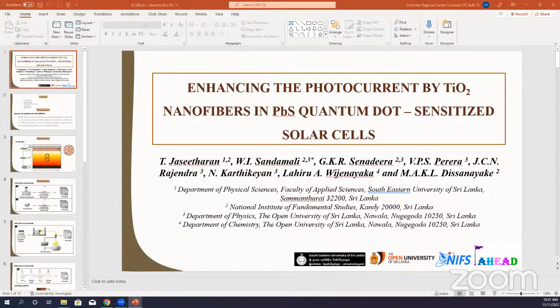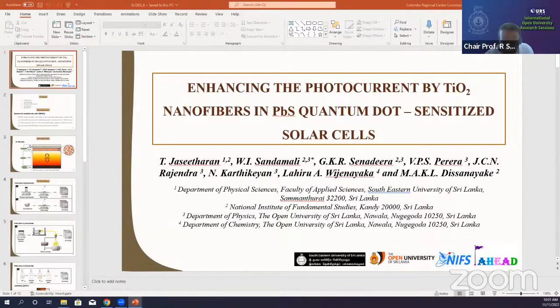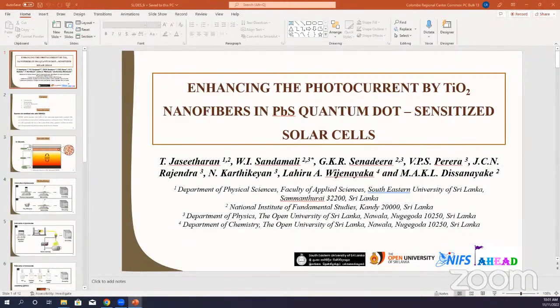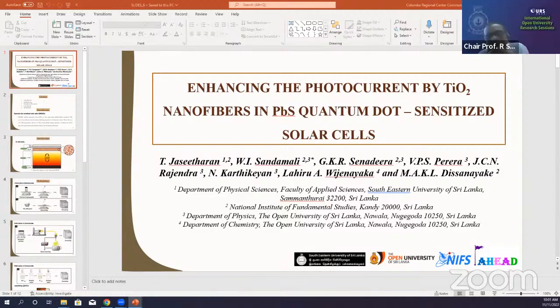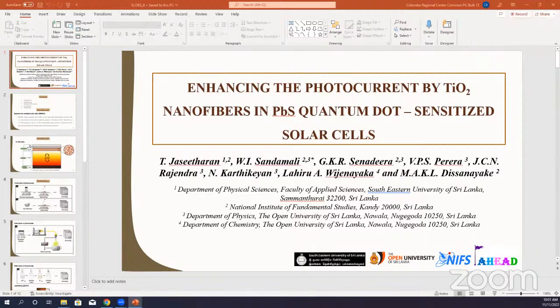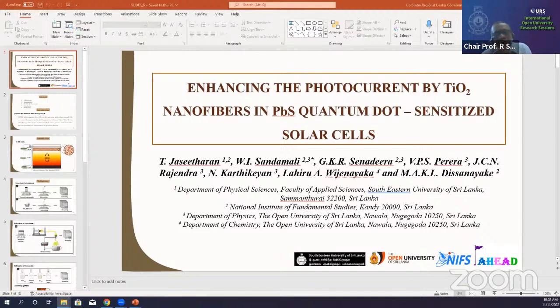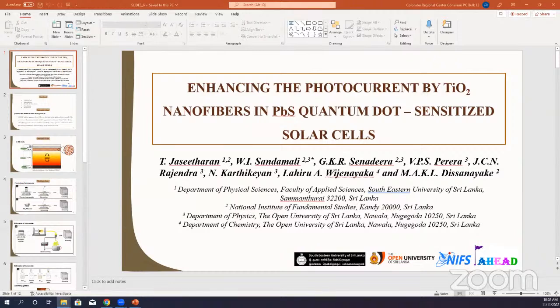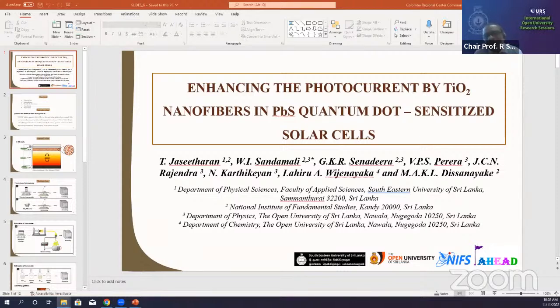Okay. And you say that in this work solar cells were fabricated using PbS quantum dot sensitized titanium oxide. How did you do the fabrication? Did you use any solvents? We used the SILAR cycle, chemically synthesized. We had the two precursor solutions, Pb2+ solution and S2- solution, 0.1 molar. Then with the successive ionic layer adsorption and reaction method we synthesized, a very simple method, but with that method we can control the size of the quantum dots. But you are not using any organic solvents for the fabrication? No. We used only aqueous solutions of lead nitrate and sodium sulfide, just aqueous solution to form PbS.